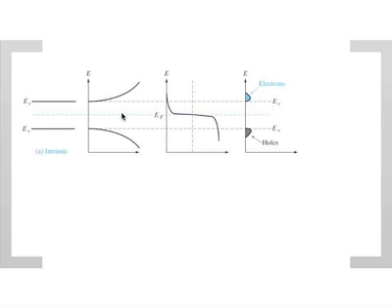Then, if you multiply these two together, so these are the available states, and this is the probability that the states are occupied. If you multiply them together and do the integration, you get the concentration. So this is the concentration of electrons and the concentration of holes in an intrinsic semiconductor at room temperature. Of course, we know this from previous discussion.